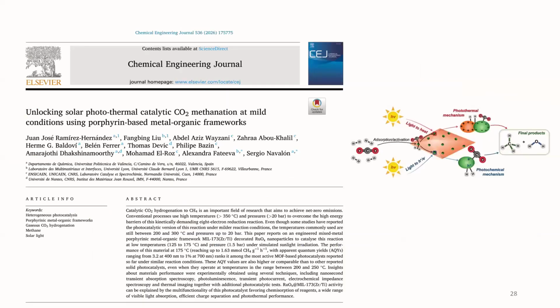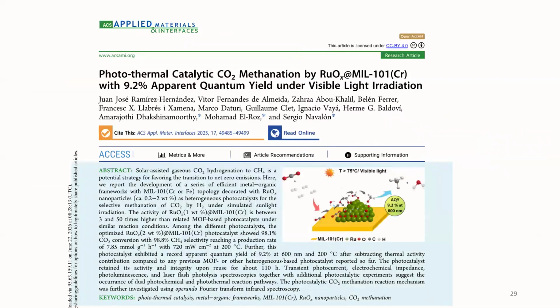And recently we reported one MOF, MIL-173 zirconium titanium. In the previous example we decorated the ligand, and in this case we just put two metals in the MOF, and this showed roughly 1.63 millimole per gram per hour. So this activity is even higher. In another example, we loaded ruthenium oxide on MIL-101 chromium, which exhibited a record apparent quantum yield of 9.2 under visible light irradiation, and here the activity was 7.85 millimole per gram per hour. So we have drastically increased the activity from 1.09 micromole to 7.85 millimole per gram per hour, and this is the highest value reported so far in the literature.